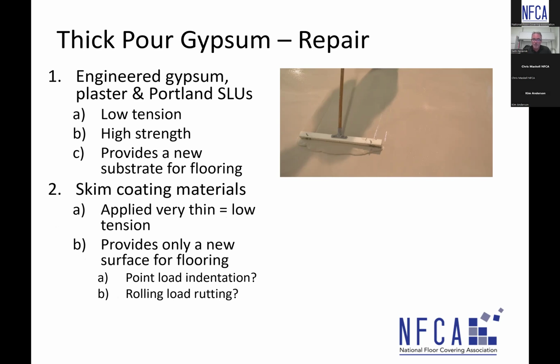Skim coating products, you may see in data sheets that the skim coating product could be used over a gypsum material, but I want you to keep a couple things in mind here. Number one, the skim coating products are low tension because they're applied very thin, and you don't have enough material there to really cure and create any tension. But the thing that I want you to keep in mind here is that we are only putting a skim coat down. We're only putting enough material to give the new adhesive something with good integrity to adhere to.